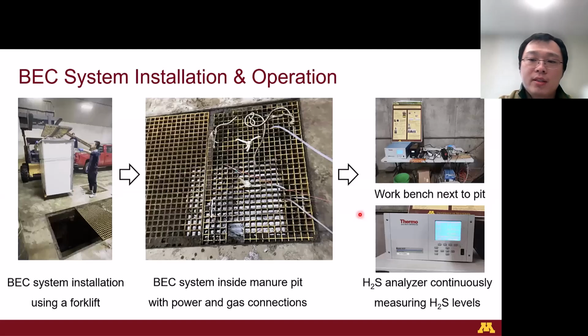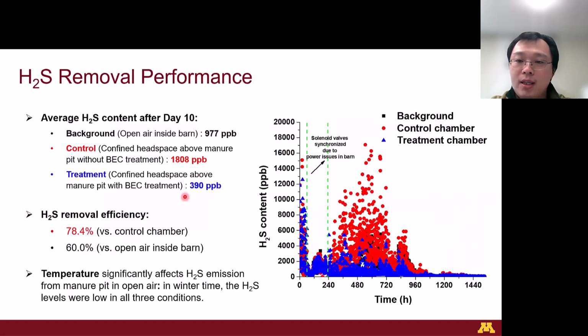The system was installed in the manure pit and operated under farm conditions for over 2 months continuously. We monitored the hydrogen sulfide levels continuously using the analyzer and tracked the change over time to evaluate the treatment effectiveness. Let's look at the results. Our pilot scale data showed a significant reduction in the hydrogen sulfide emissions.